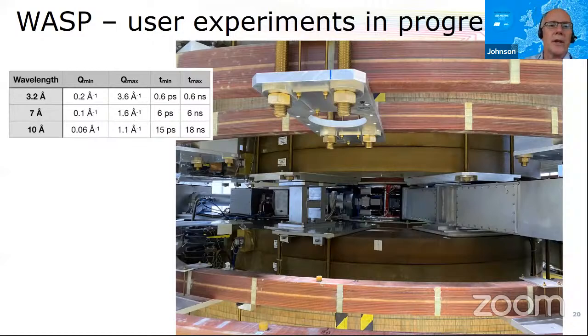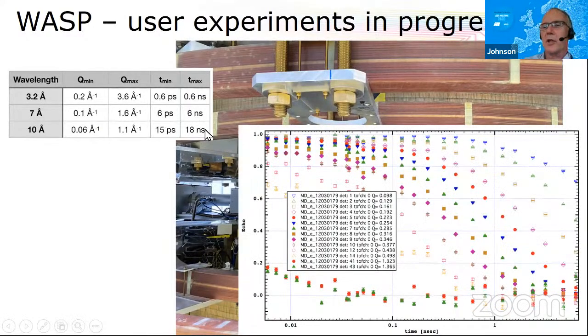So here we see a table of the characteristics. We can now cover, because of the angular coverage, a wide Q range. And when we go to longer wavelengths, we can get out to very long Fourier times of about 20 nanoseconds. And just to demonstrate that this really is working and delivering science, well, here's a set of relaxation data from a microemulsion sample, about 15 Q values measured in less than an hour. And just so that you can work out for yourselves how much better this instrument is than IN11, this type of data would have taken days to collect previously. So really the throughput on this instrument is going to be much, much higher than on IN11.